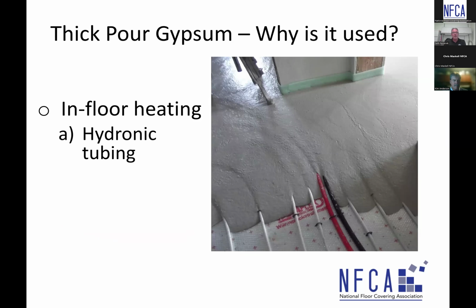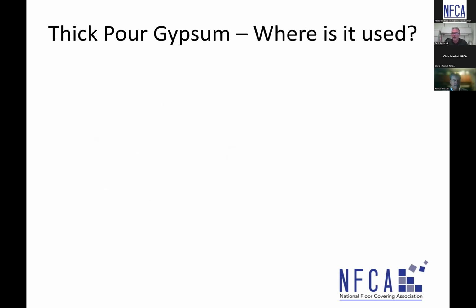Another thing that thick pour gypsum is used for is in-floor hydronic tubing. That's where they come in and install hydronic tubing on a wooden subfloor, very commonly. It could be a concrete subfloor, but very commonly a wood subfloor. In this case, a membrane was installed first, and then the hydronic tubing was installed to the subfloor and tested, and then the thick pour gypsum is pumped in at a very thick application. Again, thicker than 3/4 of an inch, and you've got to have massive material over top of those hydronic tubes. So that's another common application of thick pour gypsum. Fairly cost effective for that application. Sorry about that, I forgot I had that in the slide.